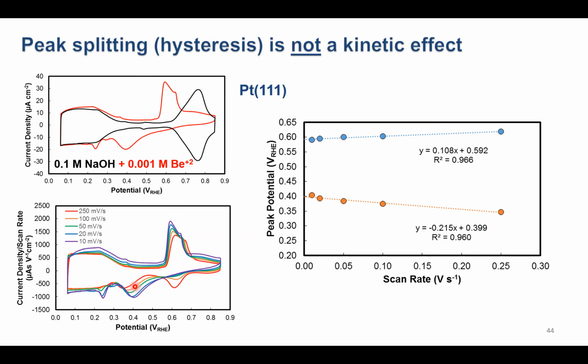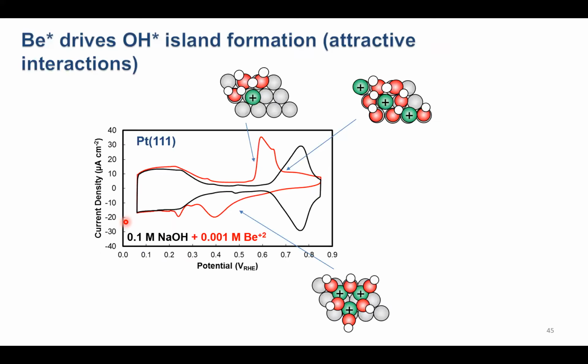What does change when we change scan rate is the relative amount of charge in this peak in the negative going scan. And you can see as we scan faster, this peak at low potentials has less charge in it, gets smaller, and this peak at high potentials starts to grow in. And this peak at high potentials does line up with the peak in the positive going scan, which actually says this process becomes more reversible if we increase the scan rate. And so this really says it's not a kinetic effect. And I think the only explanation for this is that instead it is a thermodynamic effect. And so what do we mean by that?